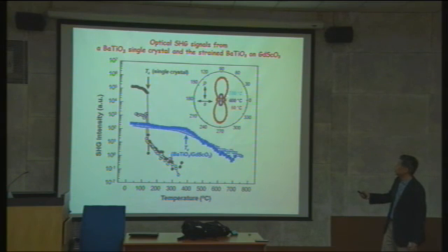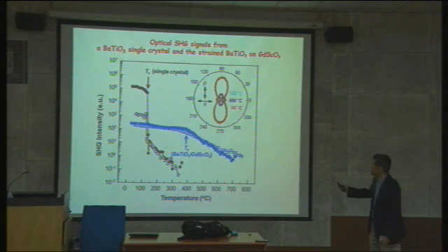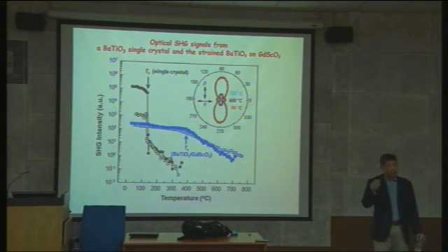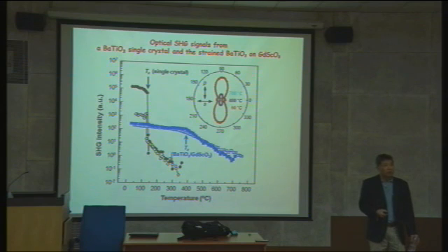So you can see at 700 degrees C, this is non-polar or centrosymmetric, and at 400 degrees C, still polar, and at 50 degrees C, very large polar, and there's a polar plot. So that is some kind of test of this strain engineering, and it's an enhancement of ferroelectricity. It's quite a large scale here. Okay, so that's something we talked about.